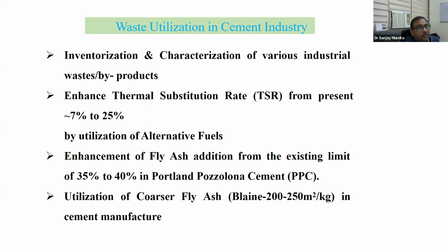And there is another lever, waste utilization in cement industry, inventory and characterization of various industrial waste byproducts by enhancing thermal substitution rate from present 7%. As I told you, the thermal substitution rate is only 7%. So we have to target in another 5 to 10 years 25%, by utilization of alternative fuels. I will show you the list of alternative fuels which industry is now ready to use and some industries are already using. Enhancement of fly ash addition from the existing limit of 35% to 40% in Portland pozzolanic cement, and utilization of coarser fly ash with Blaine of 200 to 250 meters square per kg.